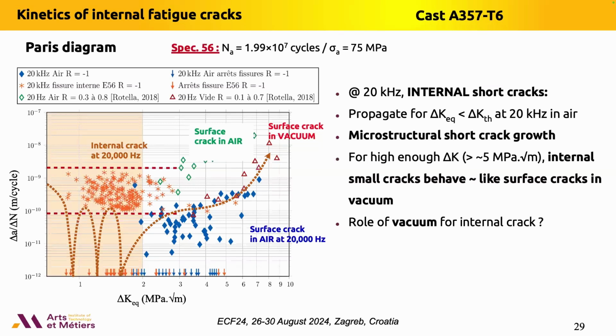And if you compare to a surface crack in air at a low frequency, typically 20 Hertz, this is data also from the literature, we see that there is a very big difference in crack growth rate. So we can keep in mind that the microstructure plays a very important role in the crack propagation. The small cracks behave inside the material like a surface crack in vacuum. So probably there is a very big effect of the environment, and we will see that in the second part of the presentation.